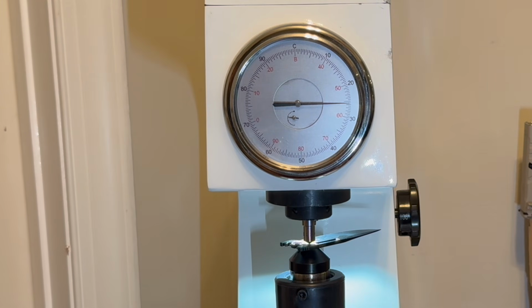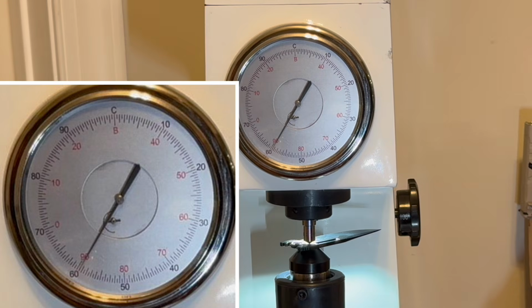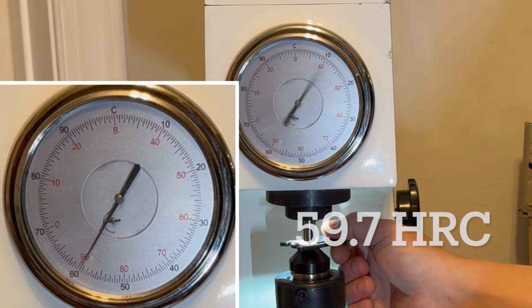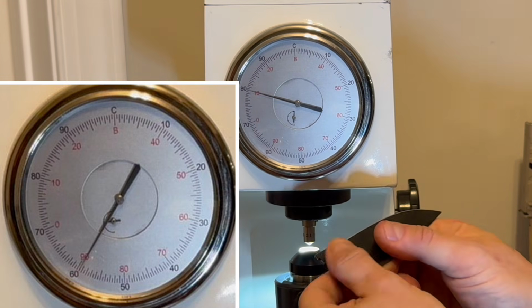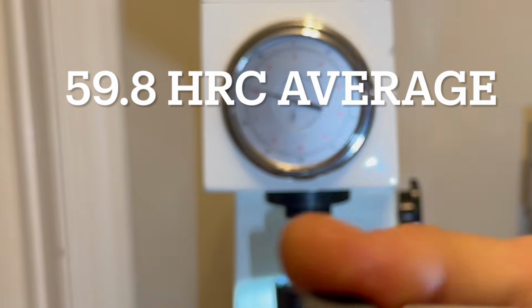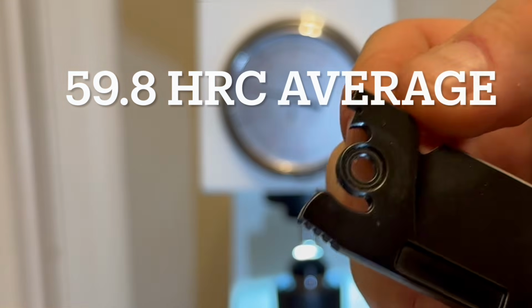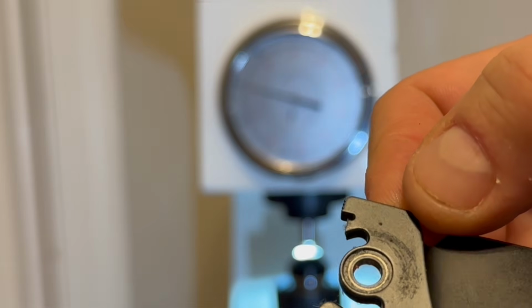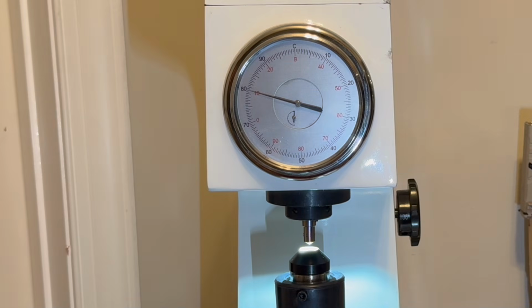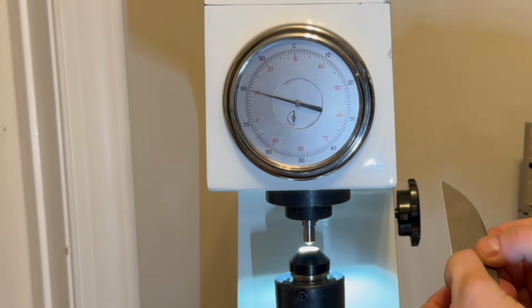The edge on an overtempered blade will roll over faster, it will dull faster, and it will bend easily when subjected to side loads. 59.7 HRC on the third poke gives us a 59.8 average. We are definitely in the acceptable range for this steel. The question to my viewers is, would you accept a slight performance degradation to get a blackout coating on the blade?